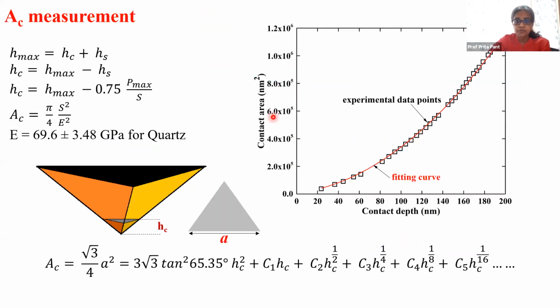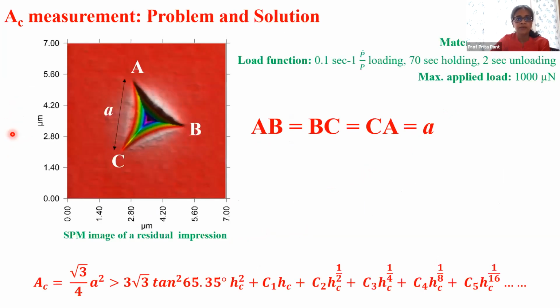So here I'm showing you data from quartz. Okay, quartz, which is not viscoelastic, which does not have adhesion issues. And here is the contact area measurement, right? We know the modulus of quartz reasonably well. Contact area goes as pi over 4 S squared over E squared. The squares are my experimental data points. This is my fitting curve and everything works well. This is my contact area that I've been able to get from this sort of an equation. Okay. But it doesn't quite work that well for SU8.